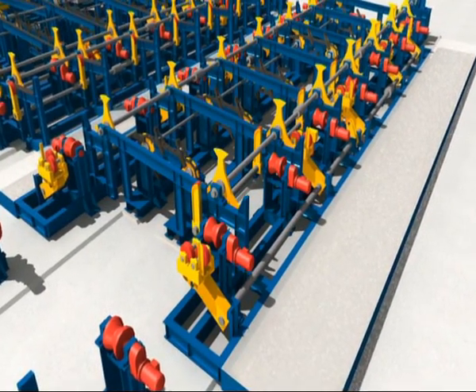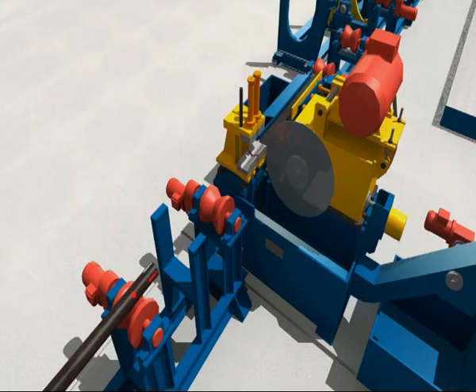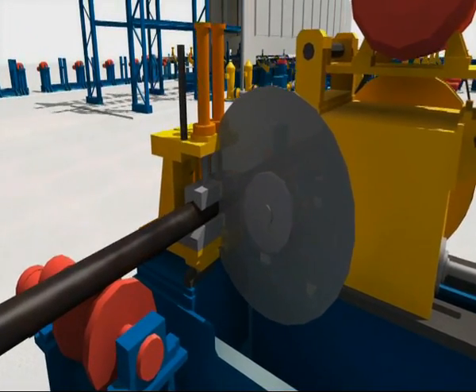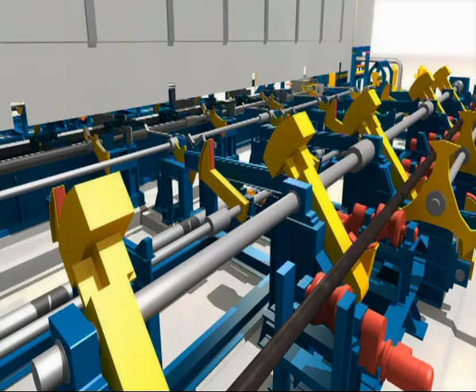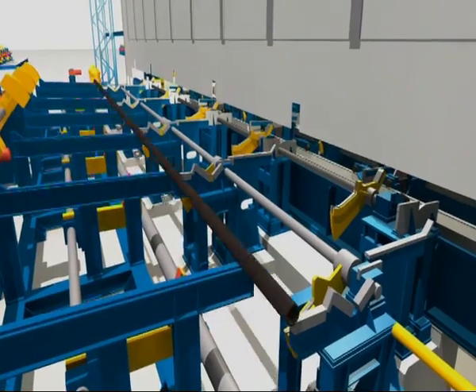According to the type of defect, repairs are carried out with a manual grinder, respecting the guidelines of the applicable specifications. Every repair is followed by a punctual recheck to verify that the pipe is still in acceptable conditions compared to the applicable requirements. In case the repairs are impossible only on a part of the pipe, the damaged part is cut. If the remaining length is without defects and is within the acceptable range, the pipe is sent to a hydraulic testing machine. Otherwise, it is disposed of for non-repairable defects. The tracking system keeps this in memory.